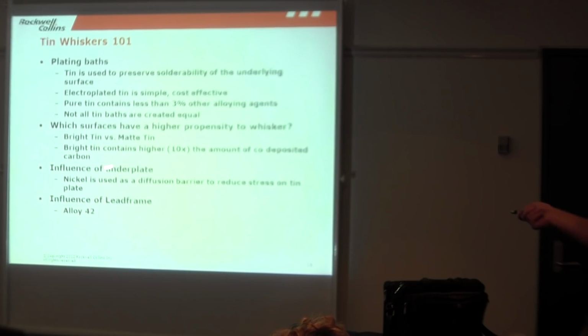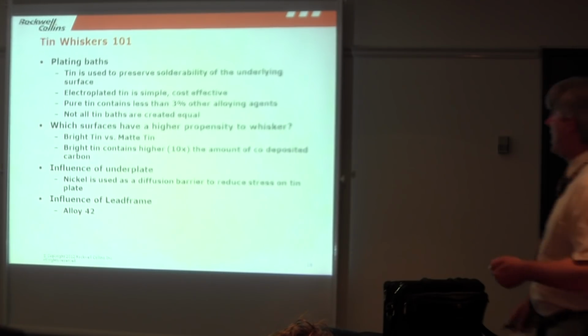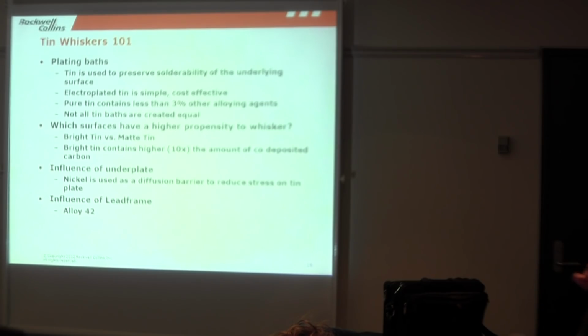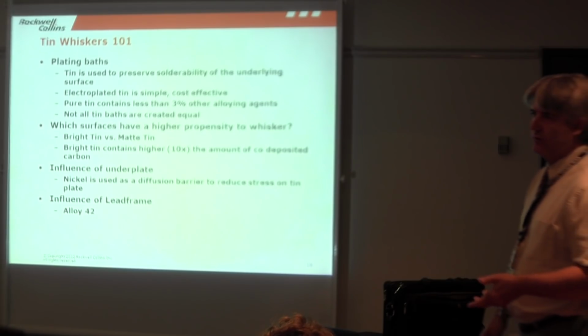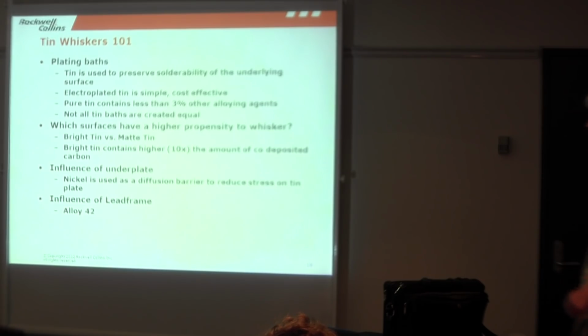Part of the reason is bright tin is bright because they co-deposit a whole lot of organics out of the bath. That's what makes it look so nice. Well, those co-deposited organics also push the stress level up in the tin through the roof. And stress in the tin plating, that's why we have whiskers. That's the number one thing that the industry has agreed upon. So you need to get away from bright tin. If you're in matte tin, you're better off. But again, we don't know, that definition varies from plater to plater.